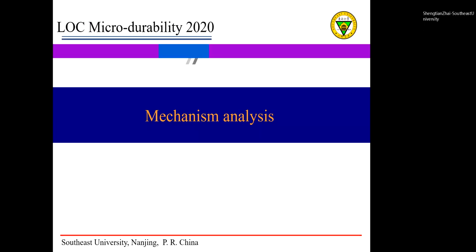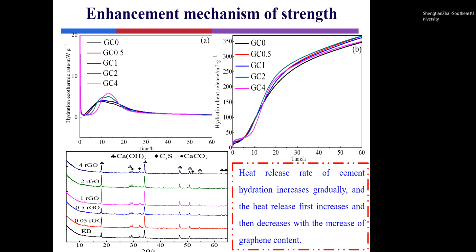Next is part 4. This picture shows the hydration exothermic curves of the mortar with the different graphene content. The result demonstrated that the exothermic rate of the samples was gradually increasing with the increase of the graphene content. The peak value was the largest when the content of the graphene is 4 weight percent, and 2 weight percent is lower. However, there is no obvious difference in hydration rate when the cement hydration entered the stable stage. This is mainly due to the nucleation effect of the graphene, which increased the contact area between the cement and water when graphene particles absorb on the surface of cement.